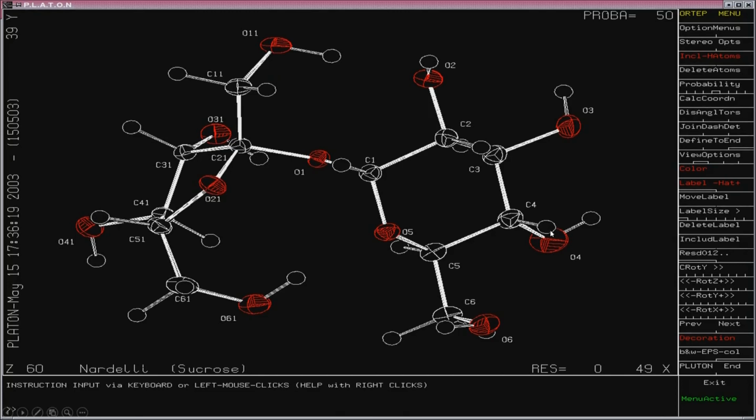So, then we do not touch the hydrogen position, but we allow the carbon, oxygen and other surrounding atoms to refine. So, whenever the new positions of these carbons come up, this hydrogen automatically is fixed again at 1 angstrom. That means this is referred to as a riding hydrogen. We call this a riding hydrogen because it rides along with this atom.